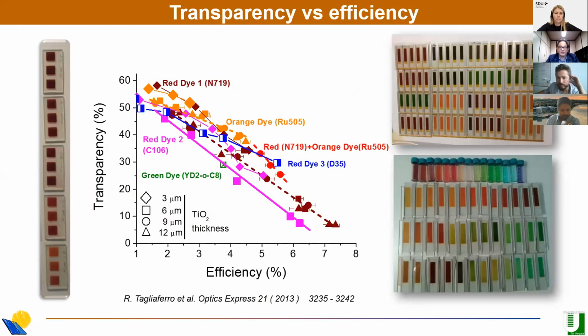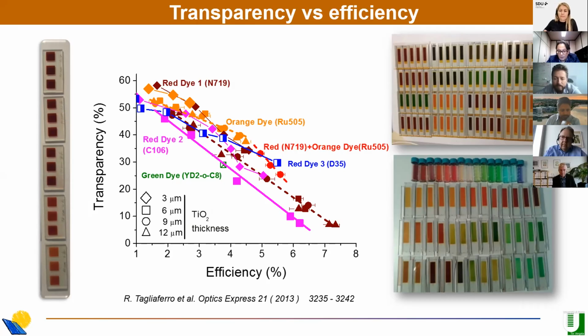So this kind of solar cell can be used for building integration because you can easily tune the color. And then you can see several colors with several transparencies. If we make a plot, which is the typical plot in this kind of application, a plot of transparency, AVT, as a function of the efficiency, you can see that by changing the dye 1, 2, and other dyes, you can change this ratio between transparency and efficiency. For example, with 4% or 5% efficiency, you can get 30, 40% of transparency. These results are from some years ago. There was an enormous effort and a breakthrough, I want to say, recently.